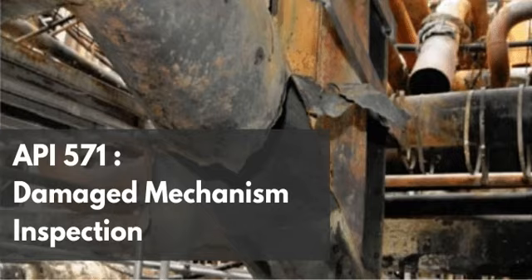And within the copper-zinc family, the text explicitly points out that the most notorious victims are heat exchanger tubes made of brass. Yes, and particularly specific grades of Admiralty brasses. Right. And I want to look at a highly specific case study that's documented here because it perfectly illustrates this. Well, let's hear it. So we have documentation of a catastrophic failure involving a very precise component. It was an inhibited Admiralty tube, UNS C44300 grade. A very common material, yeah. And it measured exactly 0.75 inches in diameter, Birmingham wire gauge 16. Which means it has a wall thickness of exactly 0.065 inches. Very thin. Right. And crucially, it featured extruded fins.